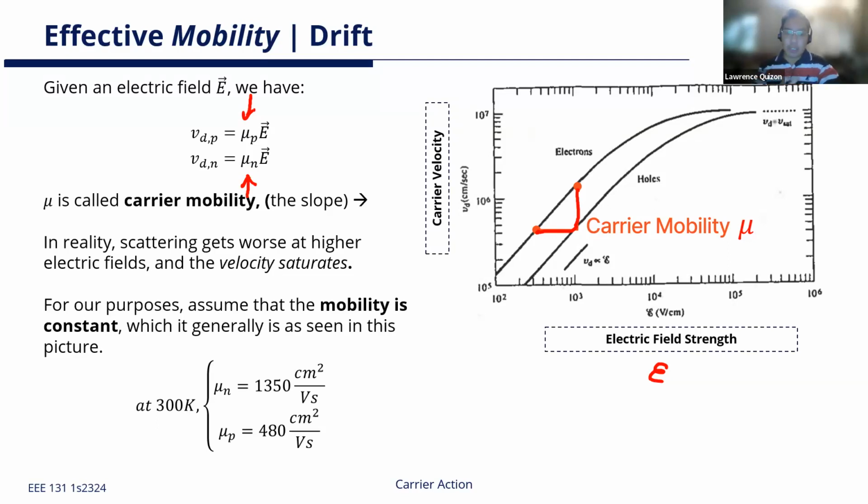It's the carrier mobility. So for silicon at room temperature, 300 K, intrinsic silicon, the mobility of electrons is 1350, mobility of holes is 480. So that's it. That is effectively what we use. That's what the experimental physicists told us they measured, no?